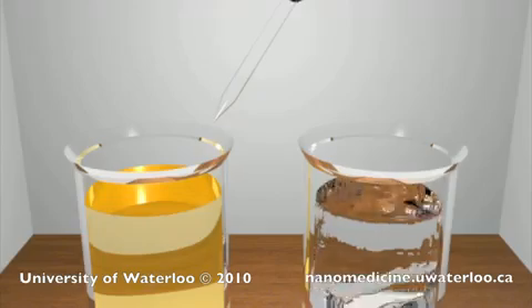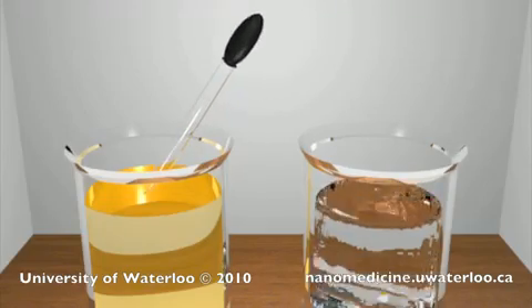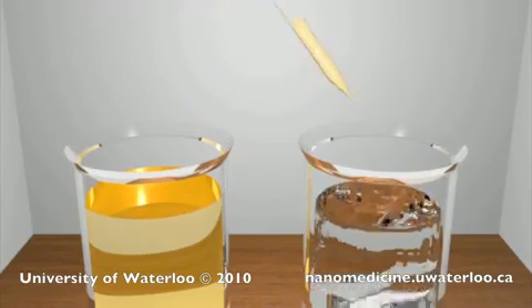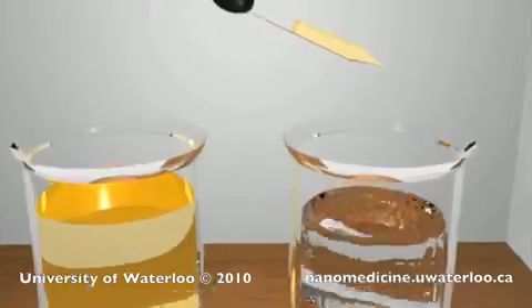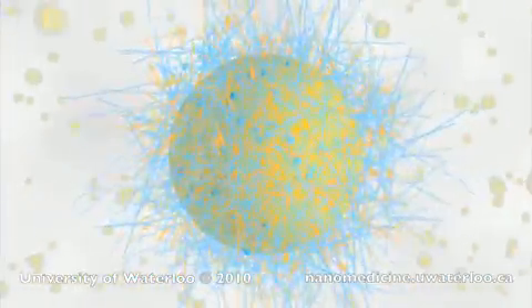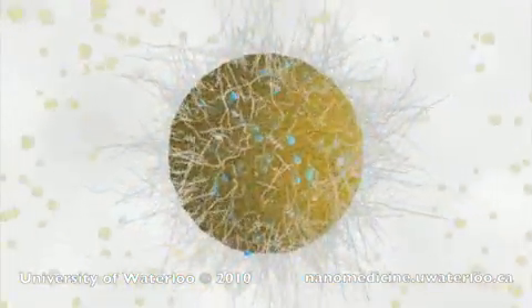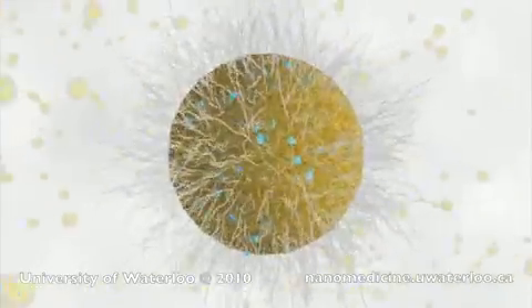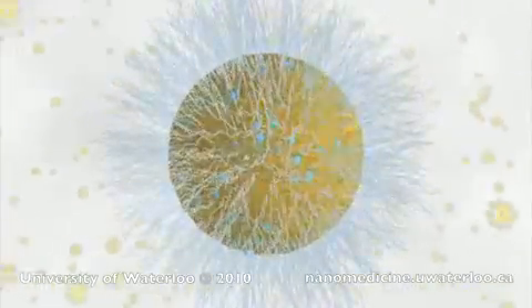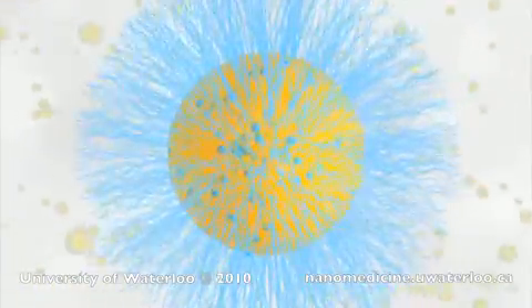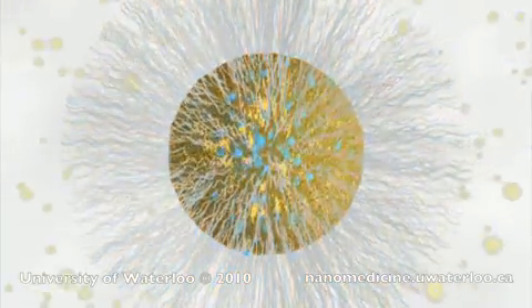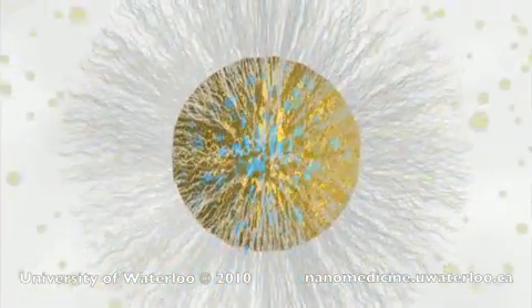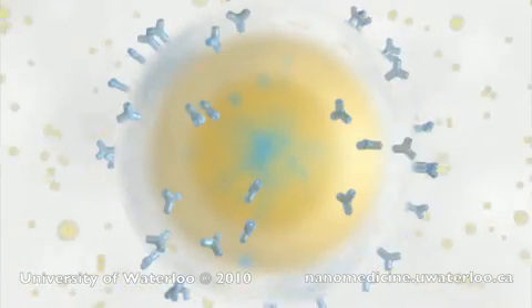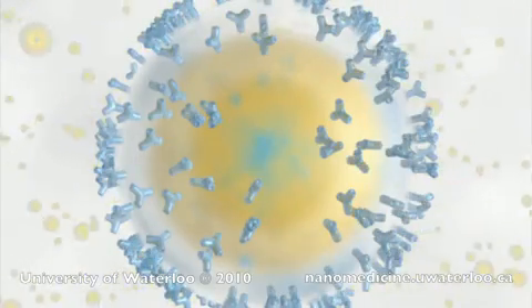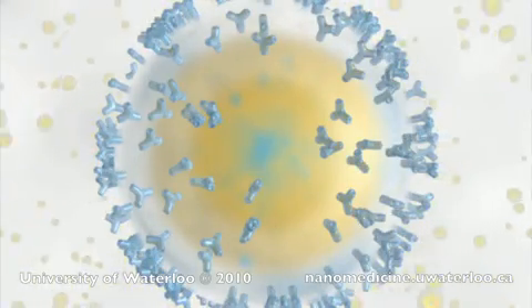Nanoparticle formation is accomplished via the dropwise addition of the organic solution to rapidly stirred water. The initially disordered copolymers rapidly self-assemble at the organic water interface of the nanodroplets, reorienting themselves so that the hydrophobic blocks are surrounded and stabilized by the hydrophilic blocks. This polymeric coating can be subsequently surface modified with various cancer-targeting ligands such as antibodies or small molecules.